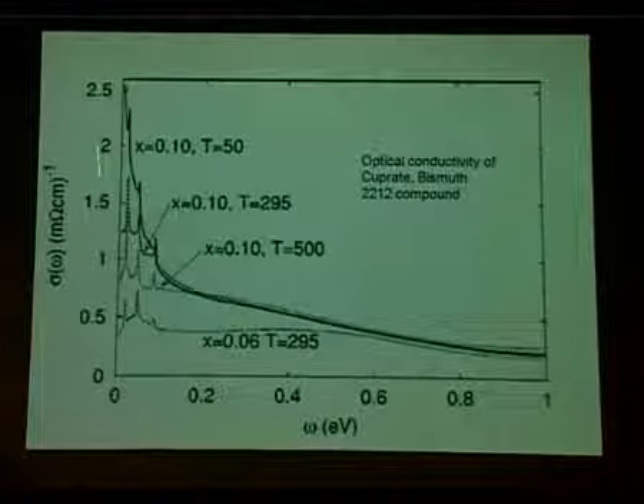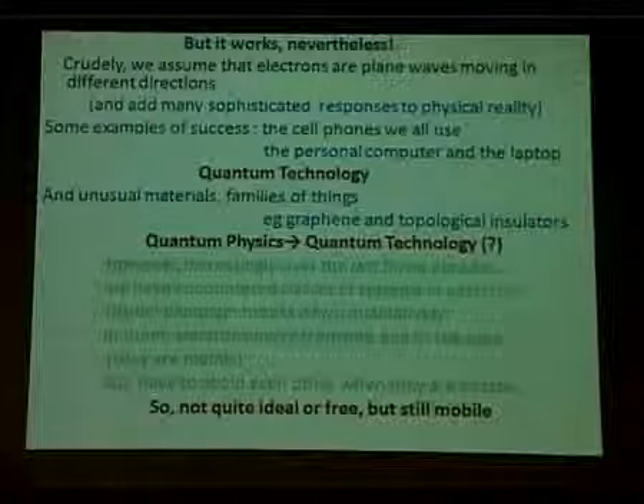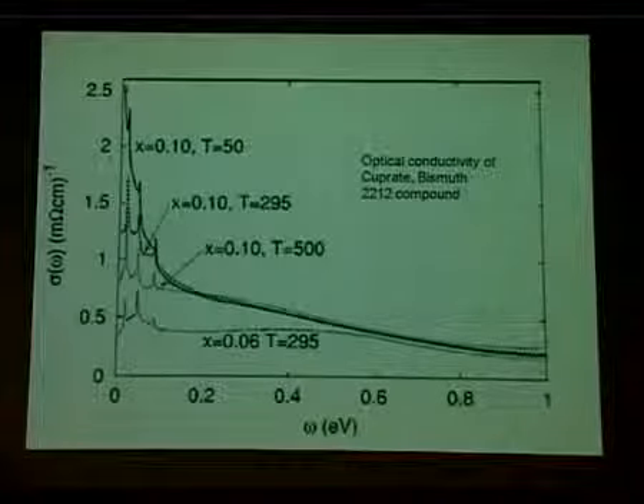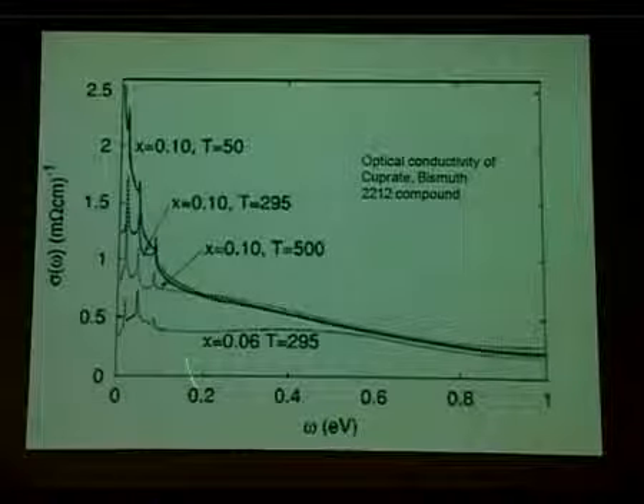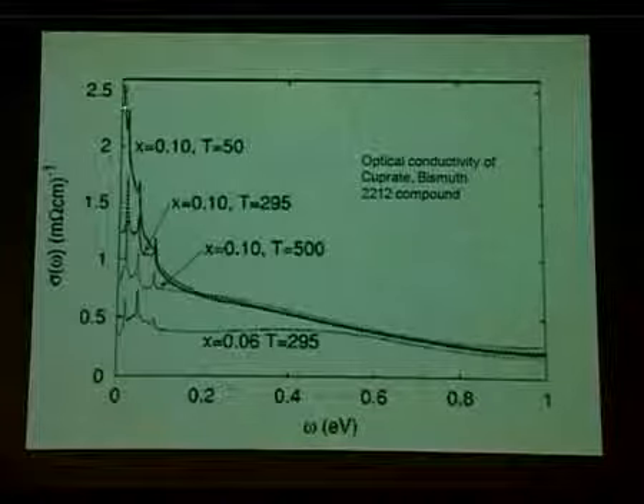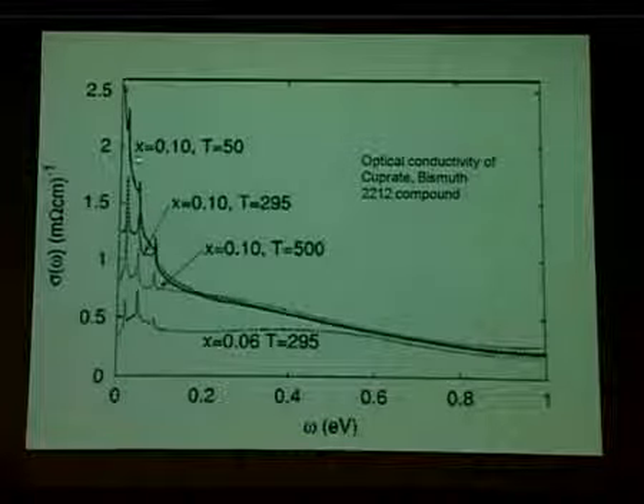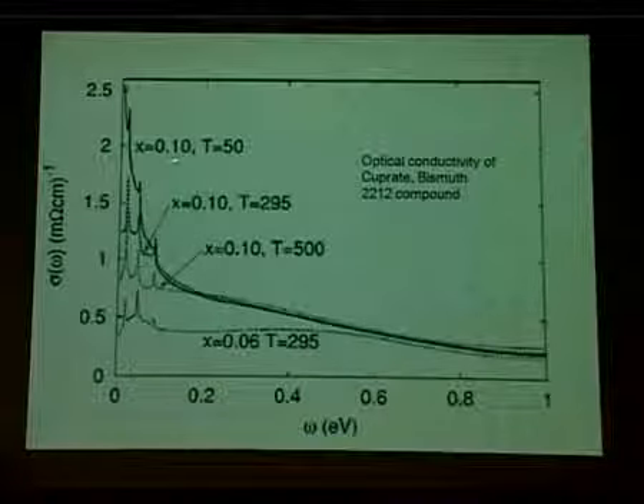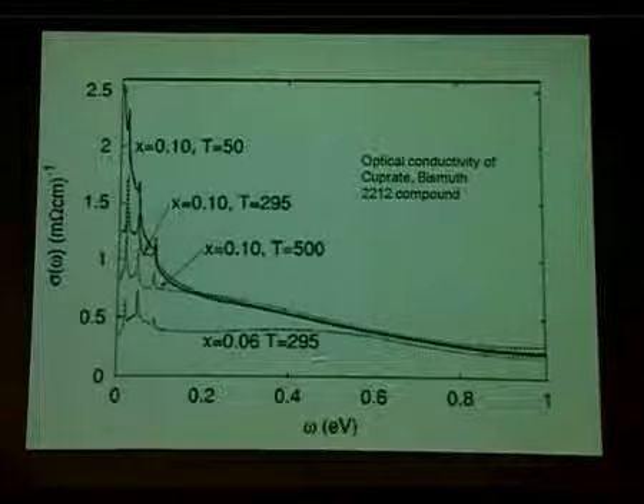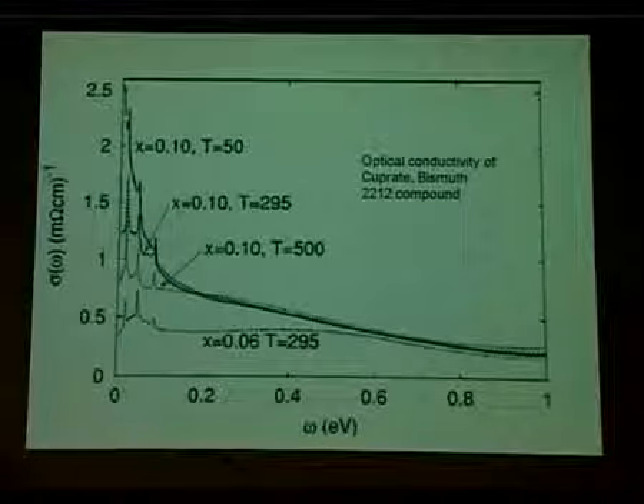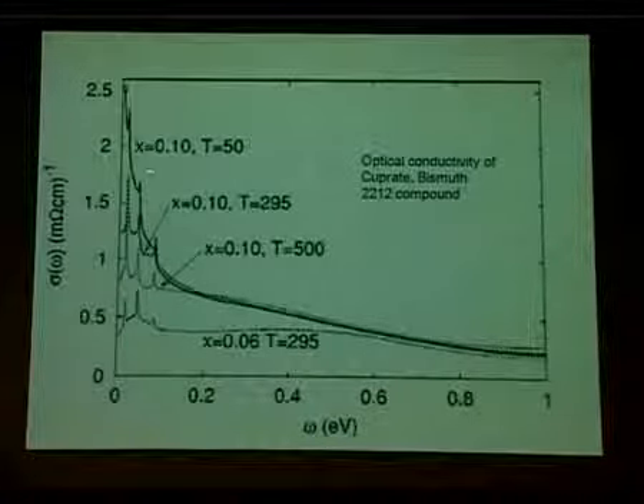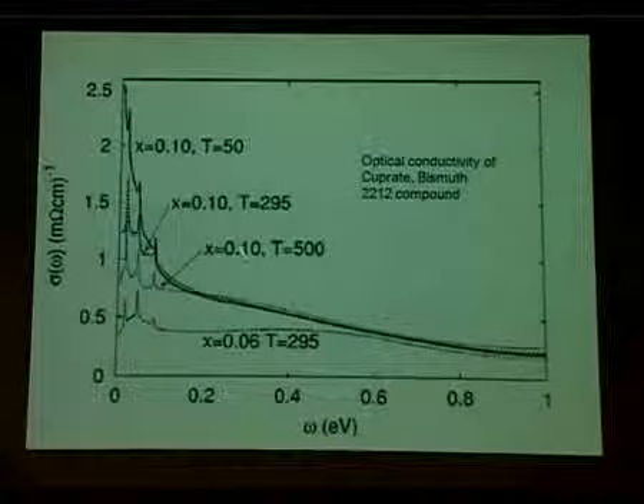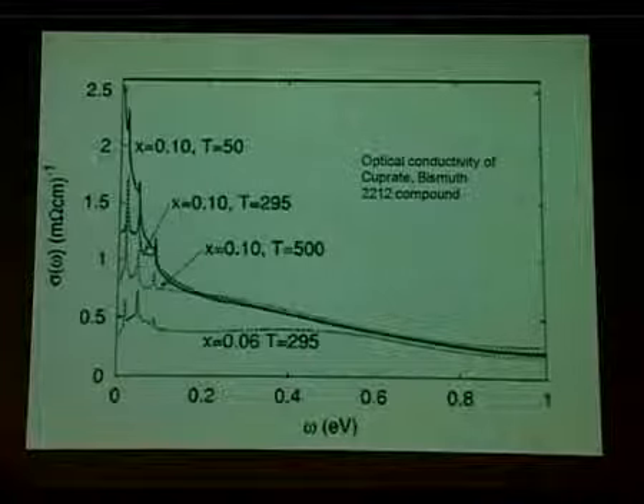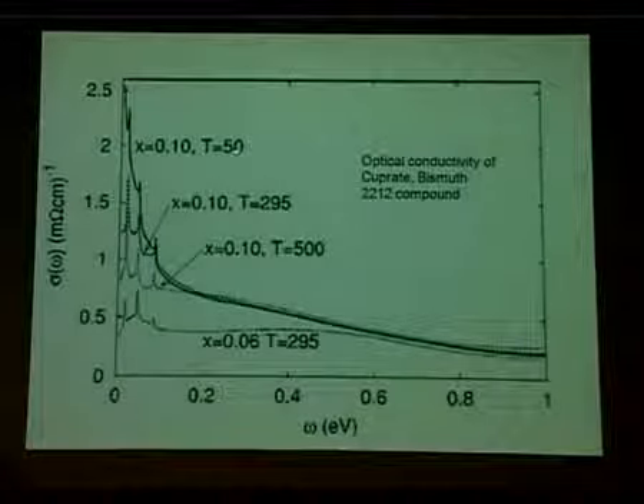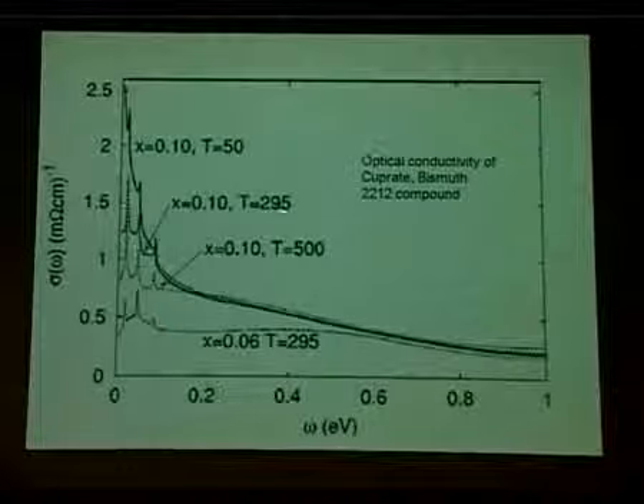So this is the real part of the conductivity as a function of frequency. Okay, let me go to the page I was talking about. Yeah, so this is the optical conductivity as a function of frequency. What we are supposed to note here again is the following fact: at a particular doping x equal to 0.1 and different temperatures, 50, 295, 500, forget this curve. It is the same compound, because the doping level is the same, just measurements done at different temperatures, 50 Kelvin, 295 Kelvin, 500 Kelvin.